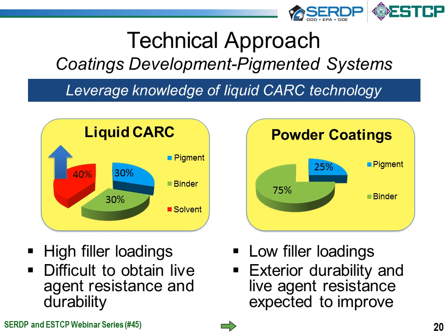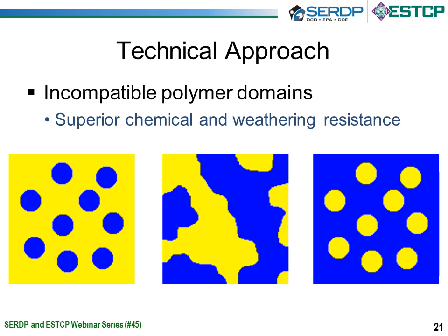So how are we able to basically flatten with low levels of pigment? Well, the key here is that we use the resin to help flatten the coating. So this is basically a cartoon depiction of an incompatible polymer. So when the polymers are incompatible by themselves, they will have a low gloss on their own. So what was important was to use low gloss resin systems combined with flattening agents at a lower level to make the powder coating. It's something that is not done in liquid CARC.